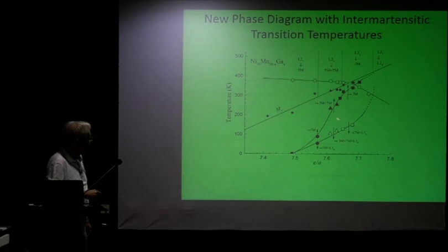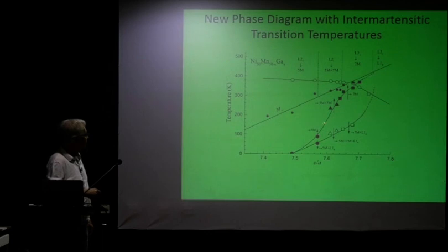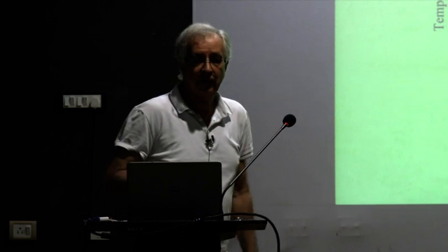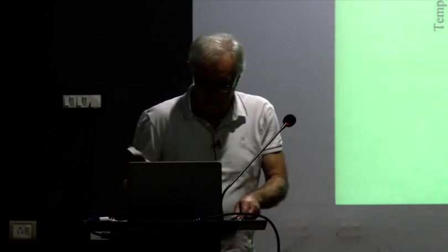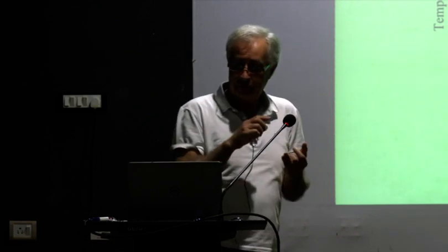This remains in this area here until you cross this. You lose the L10, and the 5m and the 7m start coming out. And if you connect all these lines over here, you find that for the 7.5 system, this remains as a 5m, and the L10 never comes out. So, this is a phase diagram, good, but what do we understand from these phase diagrams?